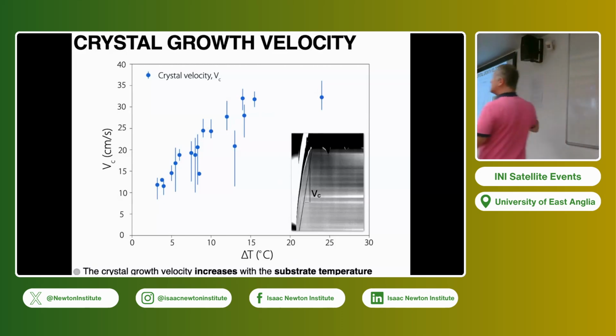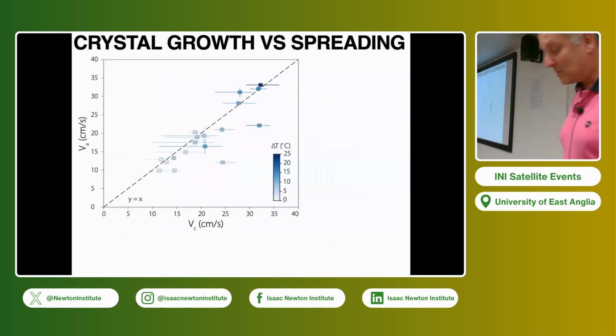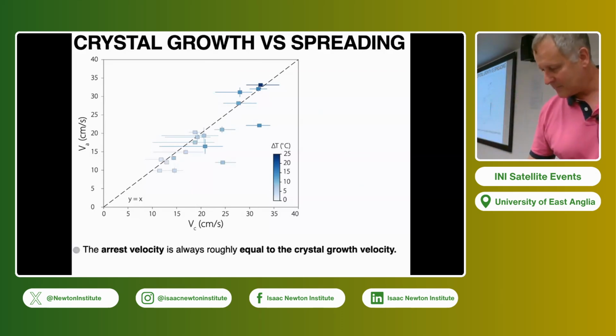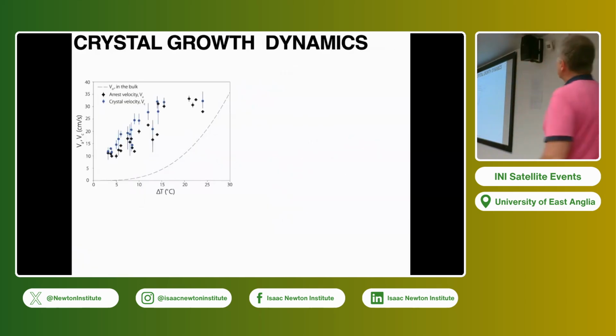We have measured the velocity of the crystal as a function of delta t, and you have this curve. If you remember, it's very close to the curve that we had for the arrest velocity as a function of delta t. We can plot the arrest velocity of the spreading drop against the crystal velocity, and we have a nice alignment on the y equals x line. Now we can plot these two velocities as a function of delta t, and it's not a full collapse, but basically the arrest velocity in black and the crystal velocity are really behaving the same. You always have an overestimate of the crystal velocity because it has to somehow overpass the spreading velocity.